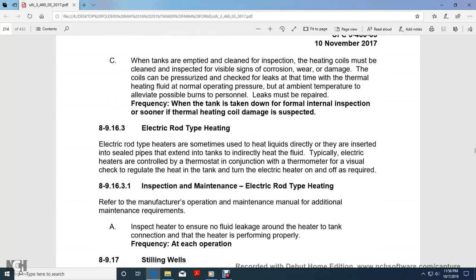When tanks are empty and air cleaned, inspect heating coils; they must be cleaned and inspected for visible signs of corrosion. Wherever damage of the coils is found, check for leaks with the coils pressurized at the normal operating pressure, but at ambient temperature to alleviate possible burns to personnel. Leaks must be repaired. Frequency: when the tank is taken down for formal internal inspection, or sooner if thermal heating coil damage is suspected.